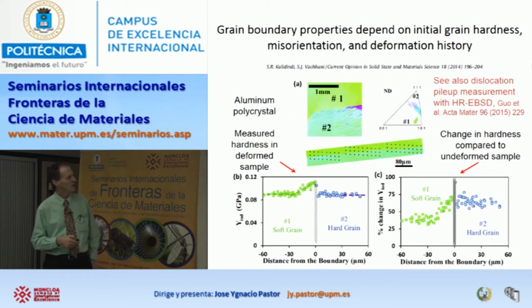Well, here's another more recent study looking at property evolution at a grain boundary. These folks have basically taken a series of nano indents that have gone across a grain boundary. And after deformation, they've investigated the spread of orientations that takes place in the grains on either side. And by just simply measuring the hardness on one side of the boundary, one sees that as you get closer to the boundary, it gets a little bit harder. On the other side of the grain, it's a hard orientation. It doesn't deform as easily as this one. And it doesn't seem to have much difference in how hard it is.